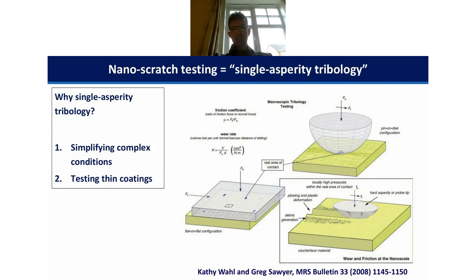So that real area of contact is a much smaller fraction of the nominal area of contact. And these contacts are therefore at much higher contact stresses. So if you really want to try and understand what's driving the deformation in your material, then it's a very useful thing to simulate these high stress contacts, and we can do that in our single asperity nano or micro tribological tests, where we have a hard asperity or probe tip sliding under very carefully controlled contact conditions.